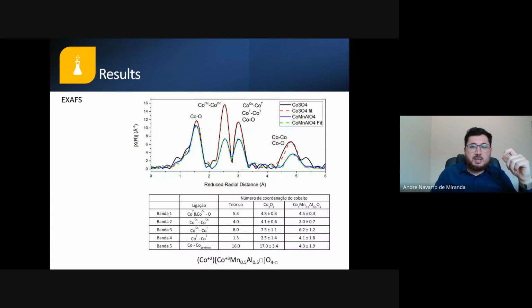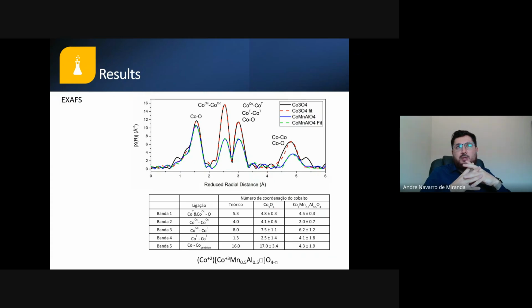between atoms. And then we did the experiment. We could see here in black Co3O4, that's the commercial form of cobalt spinel, cobalt oxide. And then when we look at the cobalt manganese aluminum oxide, the material that we are working with here, we see first a decrease in the cobalt-oxygen population. It indicates that we have oxygen vacancies in this material. So it's a really interesting result. We can see that we have some defects in this material.